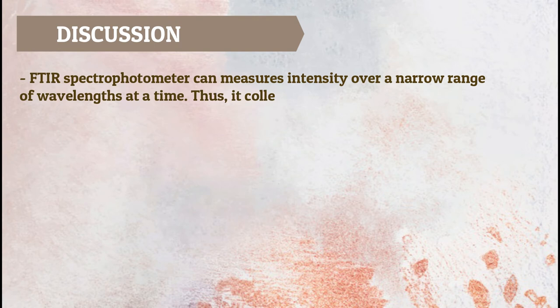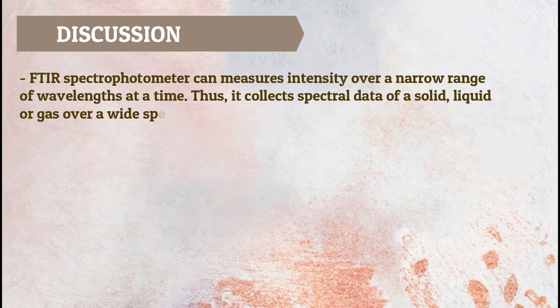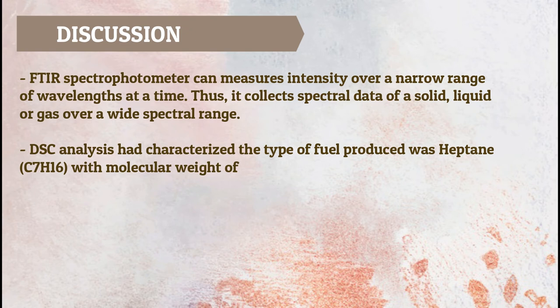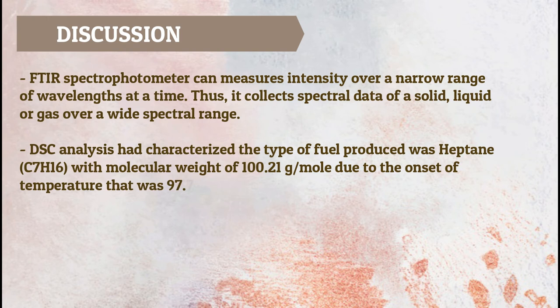For the discussion, the FTIR spectrophotometer can measure intensity over a narrow range of wavelengths at a time. Spectral data is collected from solid, liquid, or gas samples over a wide spectral range. The fuel was characterized as heptane by the differential scanning calorimeter with a molecular weight of 100.21 grams per mole.